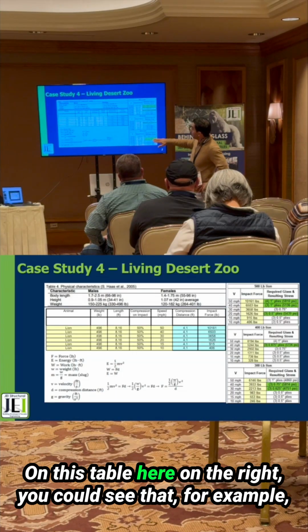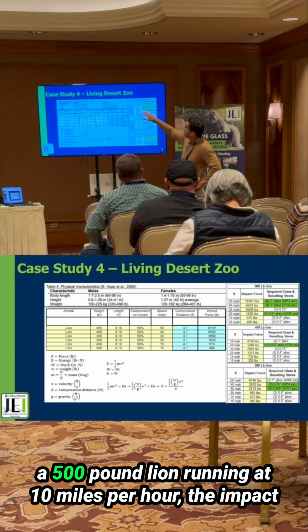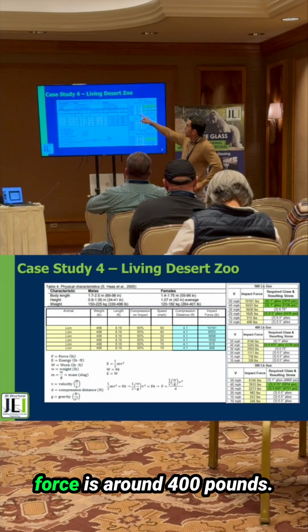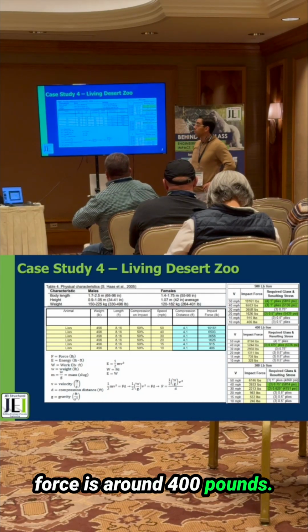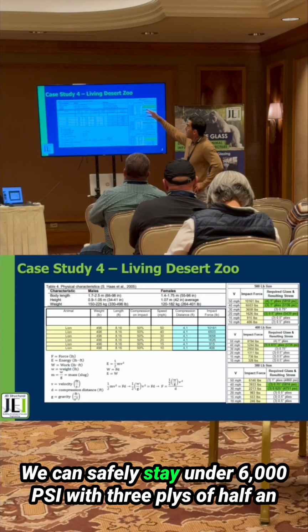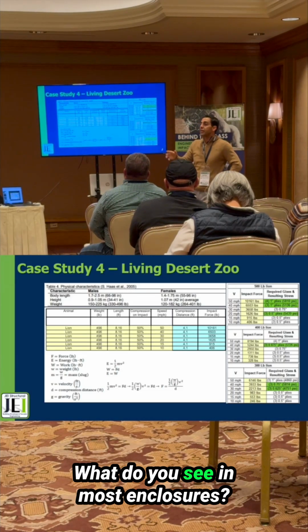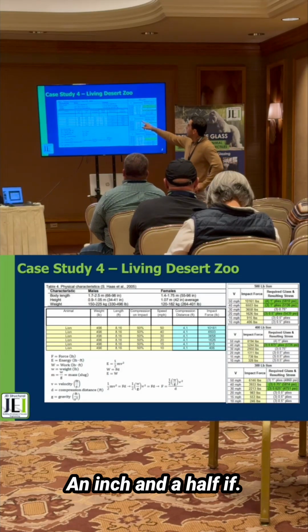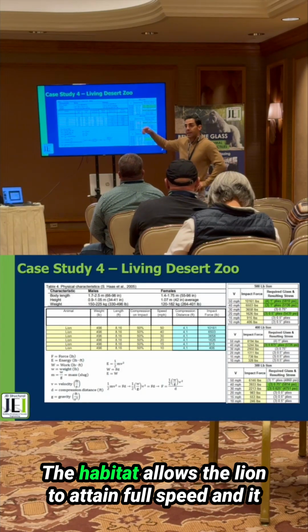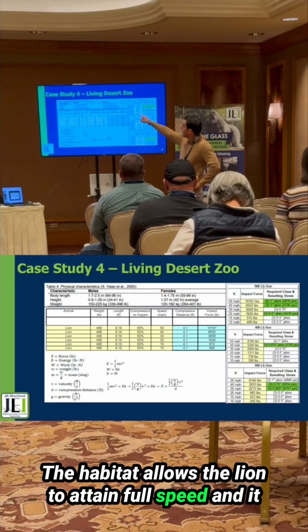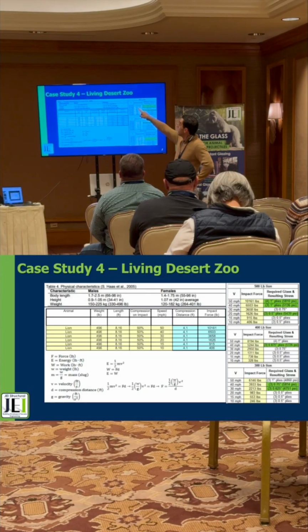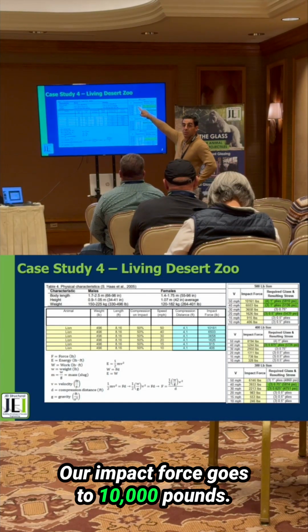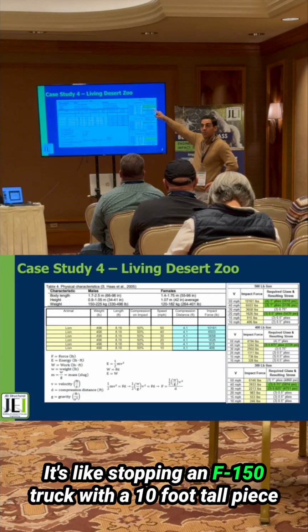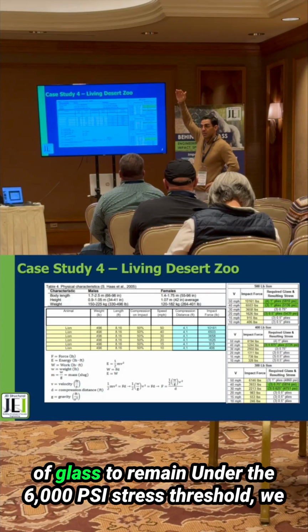On this table here on the right, you could see that, for example, a 500-pound lion running at 10 miles per hour, the impact force is around 400 pounds. We can safely stay under 6,000 PSI with 3 plies of 1/2 inch glass, so 1.5 inches. What you see in most enclosures, 1.5 inches. If the habitat allows the lion to attain full speed and it goes to 50 miles per hour, our impact force goes to 10,000 pounds. It's like stopping an F-150 truck with a 10-foot tall piece of glass.